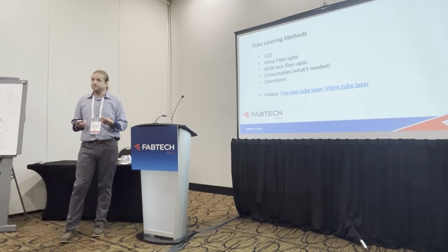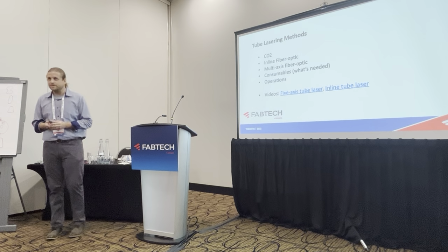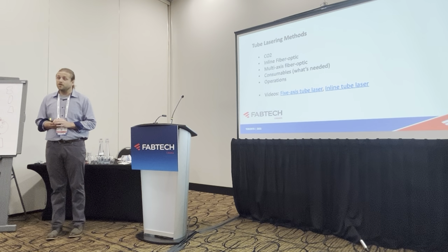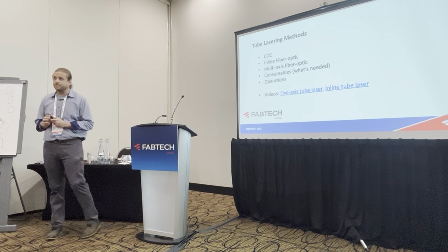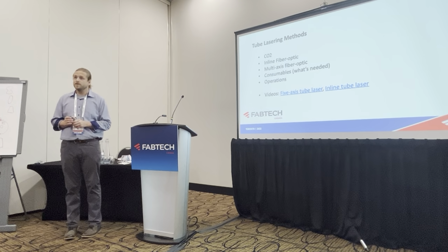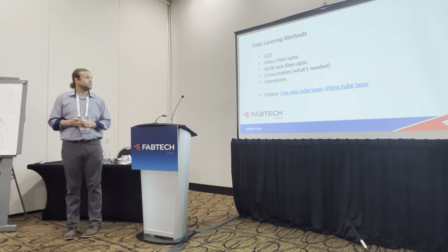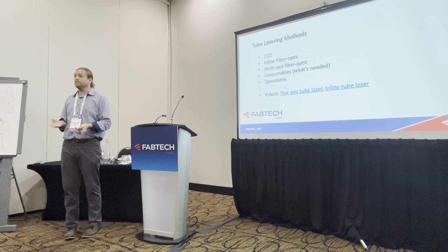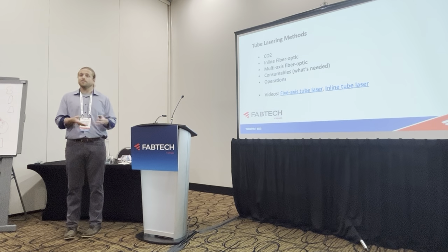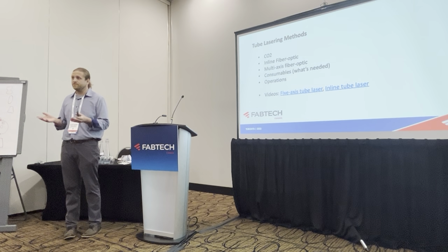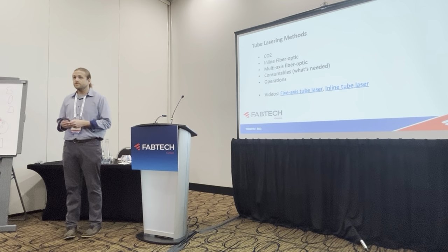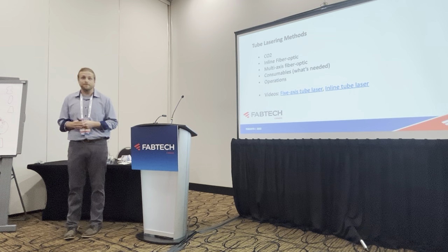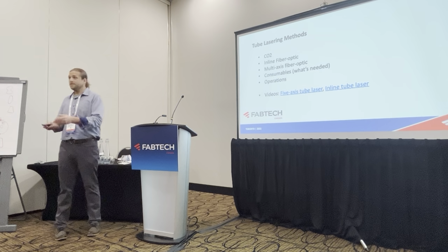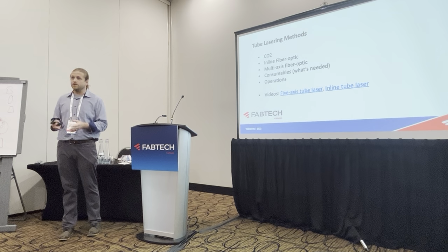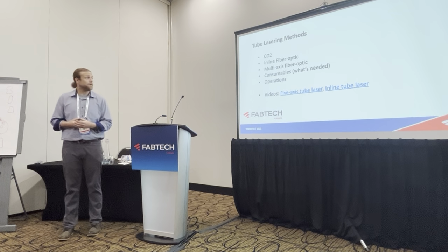So for a CO2 laser, for example, you'll probably see ranges in, you know, max probably 150 inches per minute in cut speed. For fiber optic tube lasers, you can see in the thousands of inches per minute. So that's a huge difference when it comes to manufacturing a good. You want to get it out your door as fast as you can. Throughput efficiencies is critical. So that's where the fiber laser comes in handy. It's much quicker. But again, CO2s have their place. They're really good at cutting really thick, heavy wall tubing.